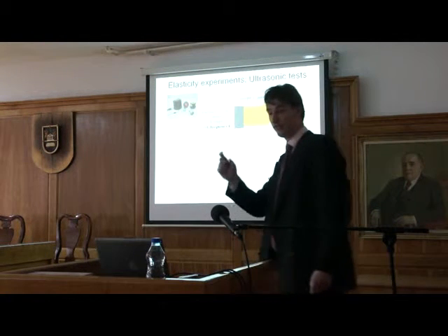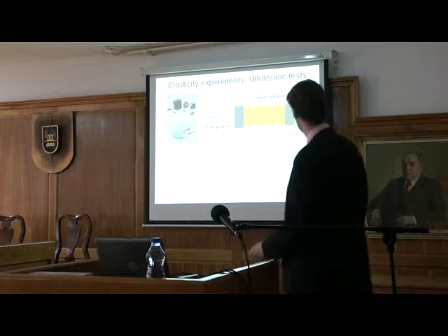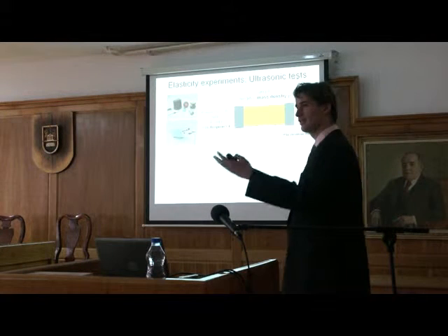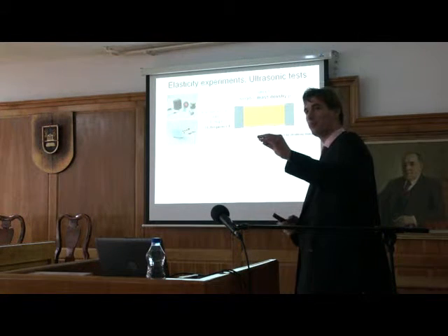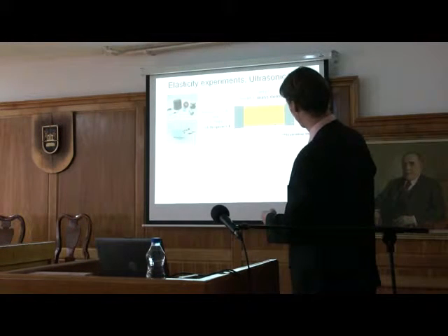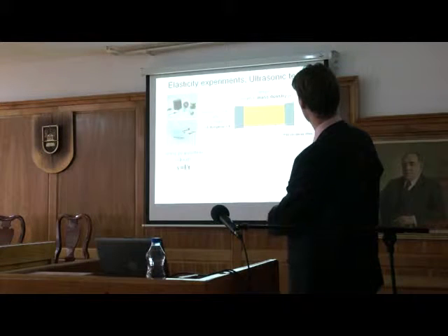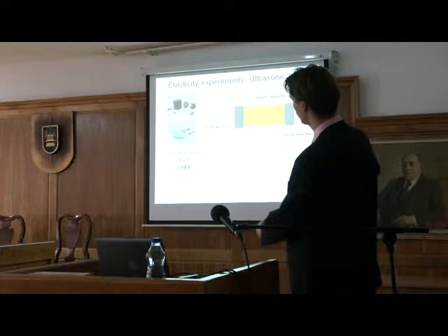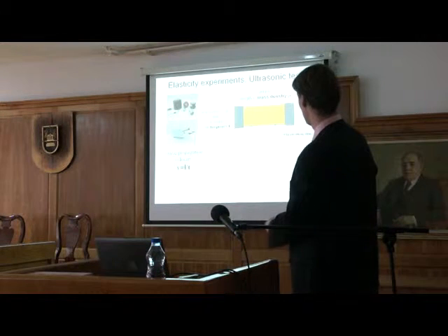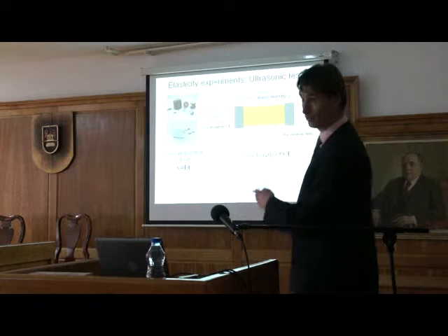The best way to test elasticity for this type of materials is ultrasound tests. First of all, because you have a lot in the literature. Secondly, because you don't have the problem with elastoplasticity because the amplitude is very small. So really you get elasticity. So the idea is you have here some acoustic signal with some frequency, you measure the velocity of the acoustic signal from here to here. From the velocity and the transit time, you get the wavelength, and now it becomes interesting.